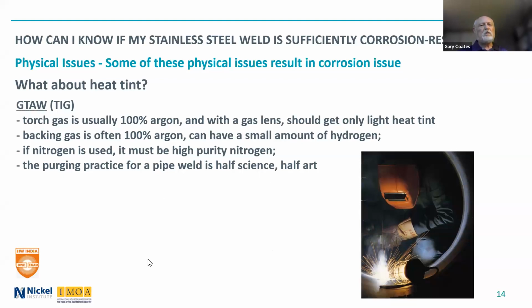And that is perfect, but purging of a pipe is really, I call it half art, half science, because getting the oxygen content right in the purge, behind the weld in a pipe, is really tricky. It's time consuming and it's costly. Nitrogen can also be used as a backing gas. However, it has to be high purity nitrogen, and I've seen many cases where people just say, "Oh, we've got nitrogen," and they'll use something that's 99% nitrogen, but has 1% other gases in there, including oxygen. So it's important to use a higher purity nitrogen if you use that as a backing gas.